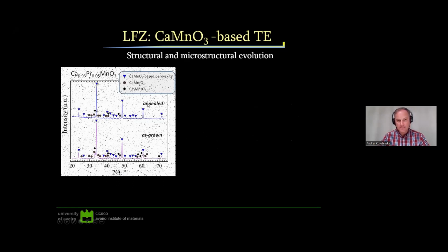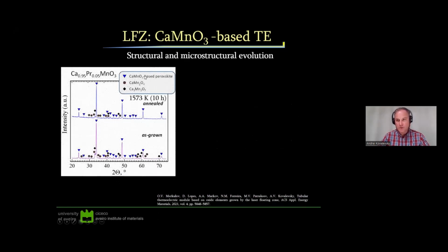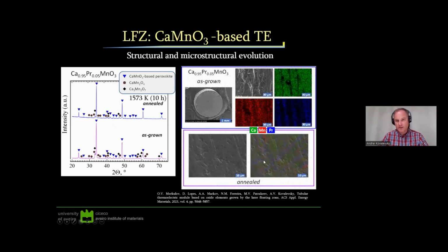These oxides are very interesting as thermoelectrics. Good news is that the desired perovskite-based phase, which has interesting thermoelectric properties, forms immediately after growth. Still, it contains a lot of impurities, and bad news is that even after post-thermal annealing, these impurities don't disappear completely, and they can affect the performance. Even for annealed fibers, we have quite significant chemical inhomogeneities, which, as I will show you later, affect the thermoelectric performance.